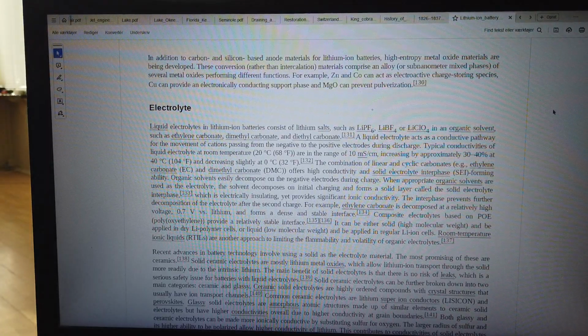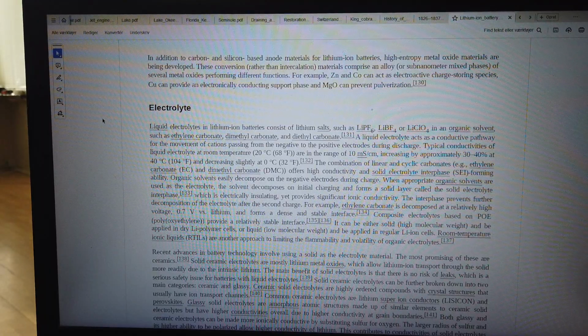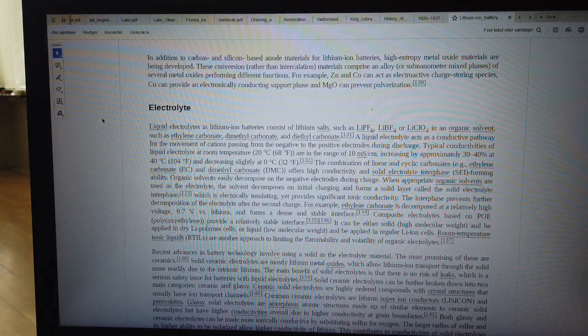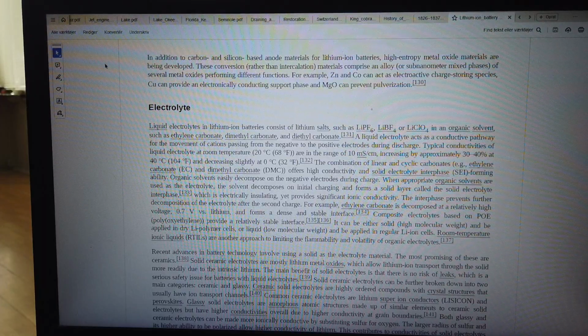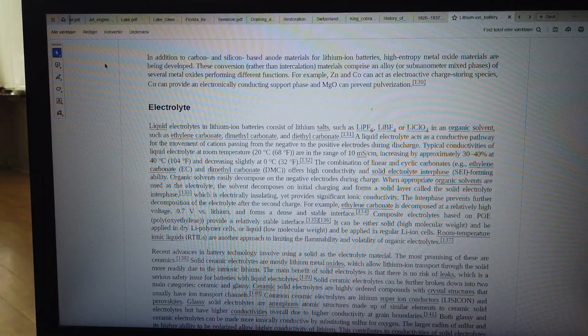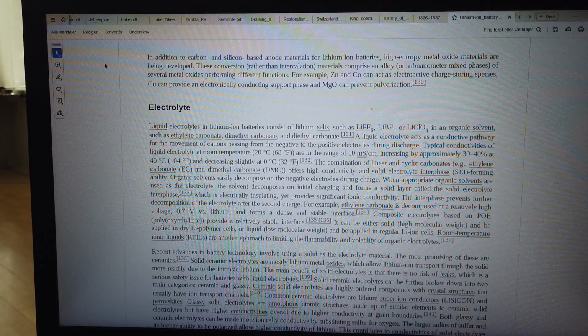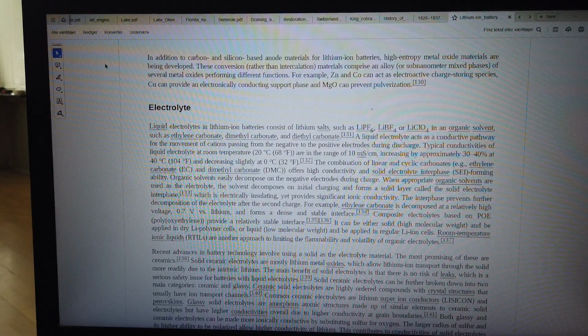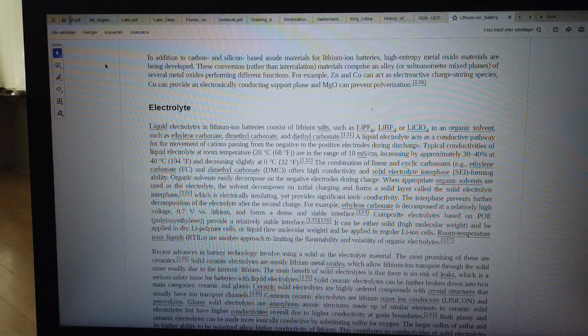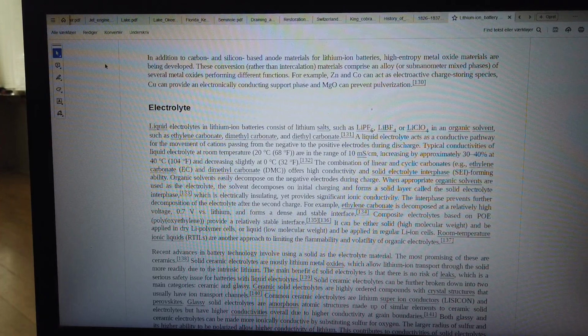In addition to carbon and silicon-based anode materials for lithium-ion batteries, high-entropy metal oxide materials are being developed. These conversion, rather than intercalation, materials comprise an alloy, or subnanometer mixed phases, of several metal oxides performing different functions. For example, Zn and Co can act as electroactive charge storing species. Cu can provide an electronically conducting support phase, and MgO can prevent pulverization.